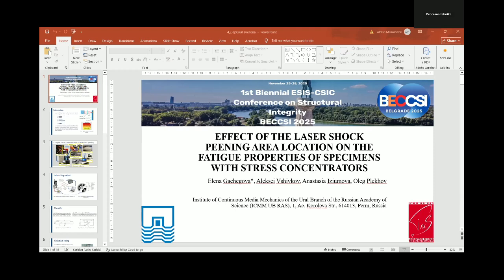The fatigue properties were studied, like Aleksei said, using the servohydraulic testing machine, under conditions of axial cyclic deformation with a cycle asymmetry coefficient of 0.1 and a maximum cycle load of 8 kilonewtons. Crack length monitoring during the fatigue test was performed using the potential drop method, which enables continuous real-time tracking of crack growth. A little bit more about this method.